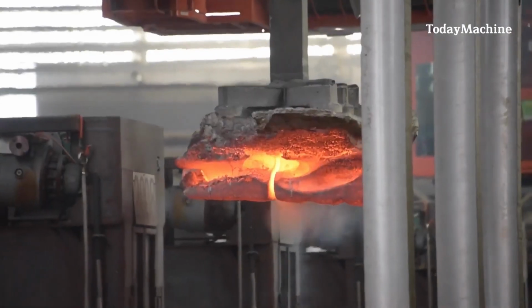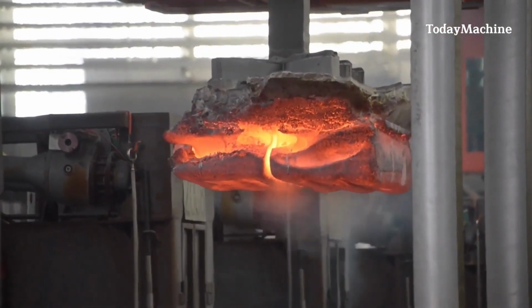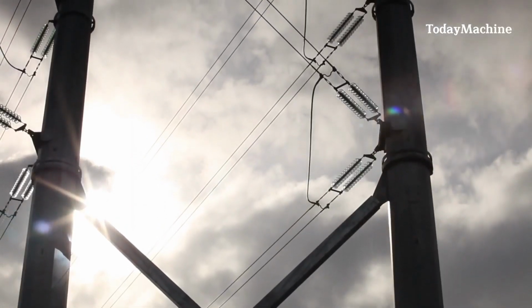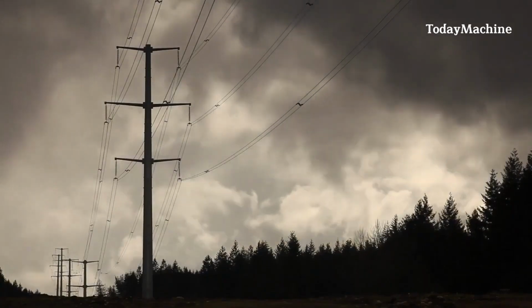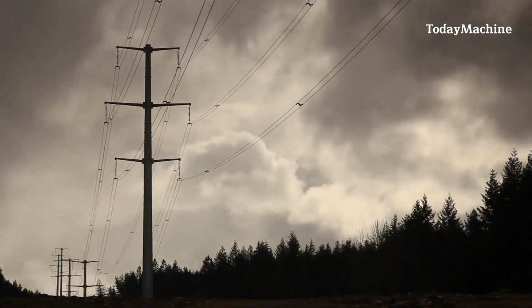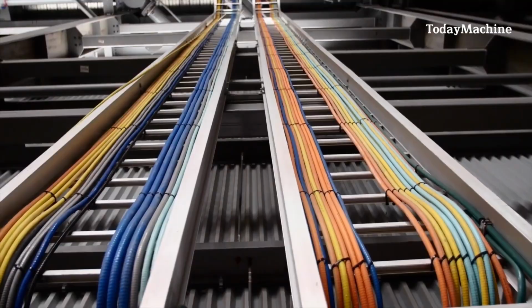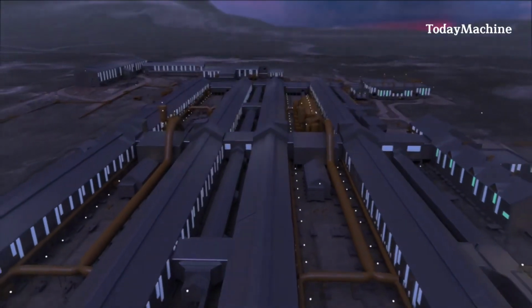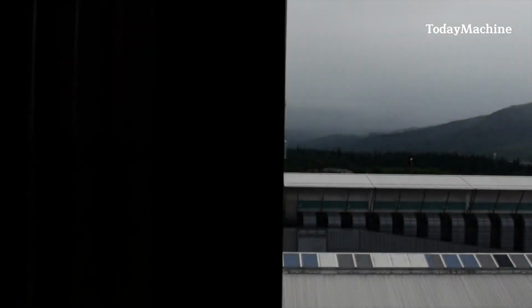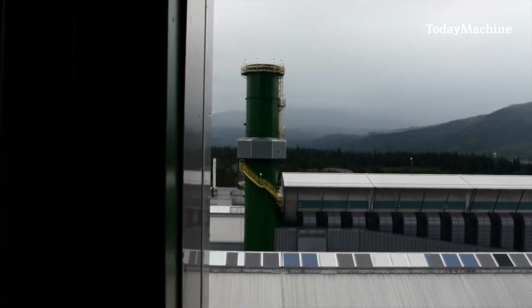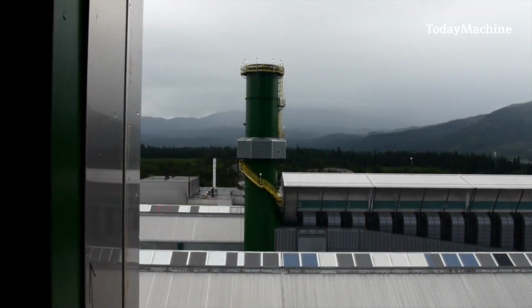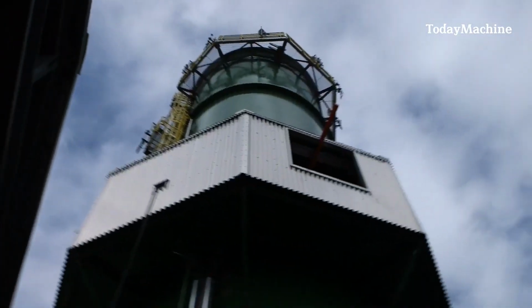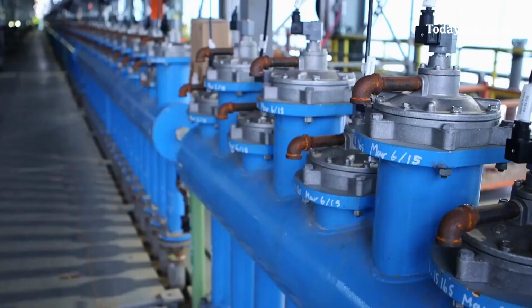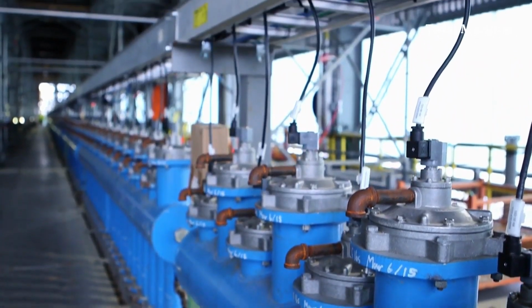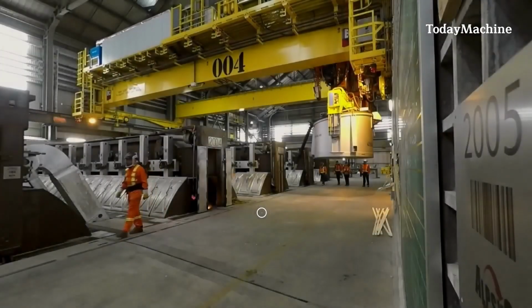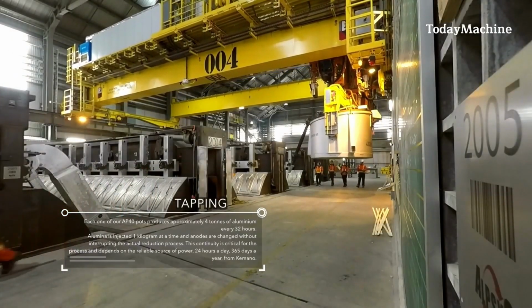These anode assemblies are made from baked carbon blocks. Carbon blocks are produced on site in the carbon cell facility and undergo a baking process in a dedicated bake furnace. The anodes are baked at temperatures of up to 1,200 degrees Celsius for about 20 days. Over 600 pre-baked anodes are produced daily to ensure a continuous supply for the smelting operation. The anodes are transported to the pot rooms where they are installed in the pots.